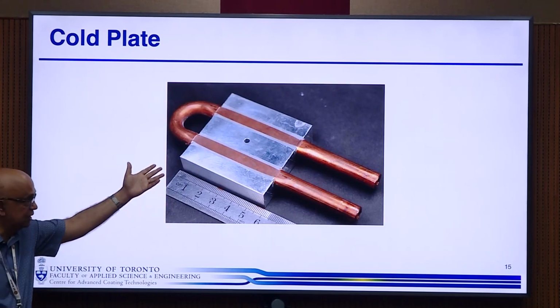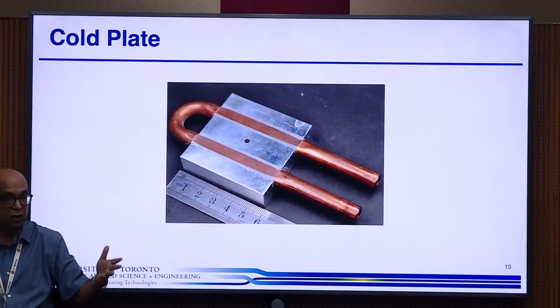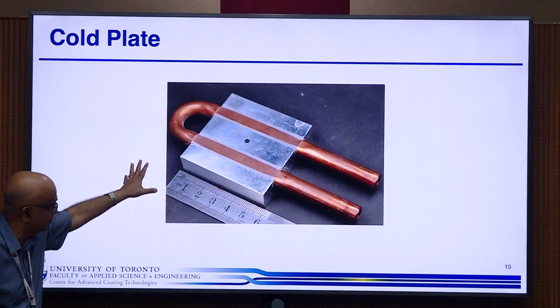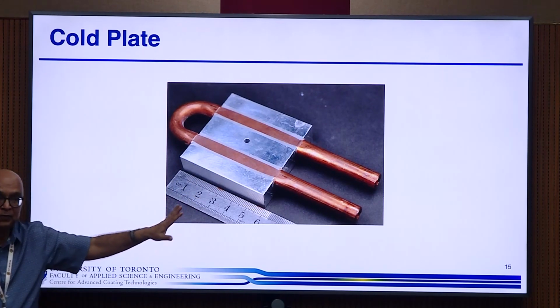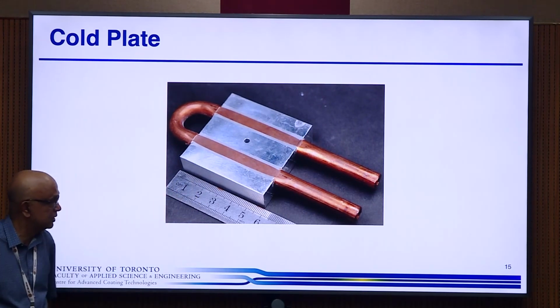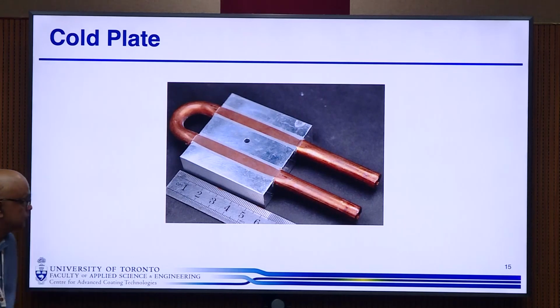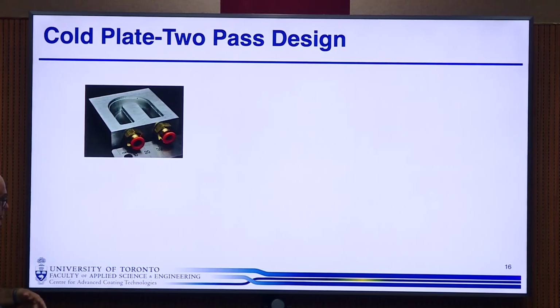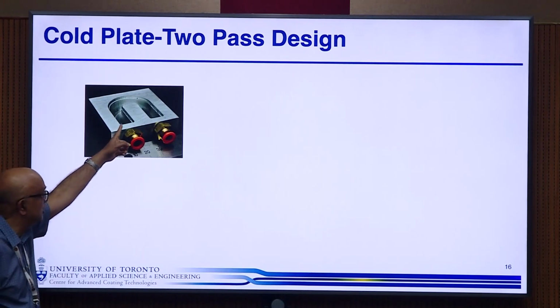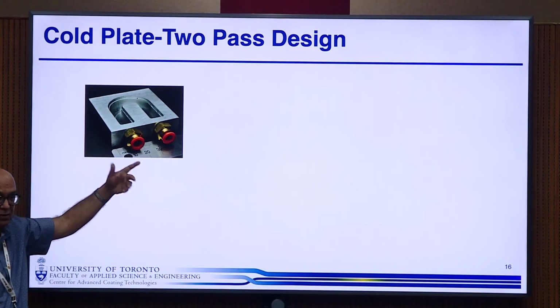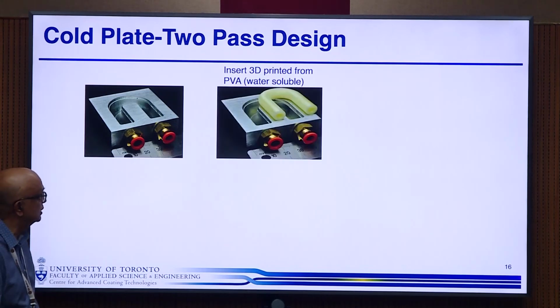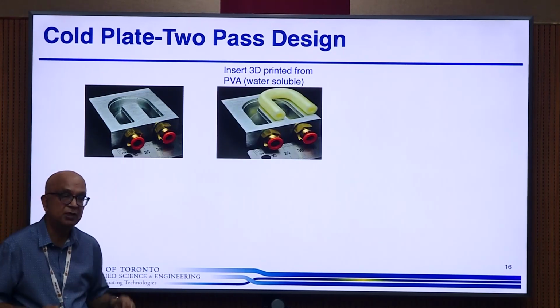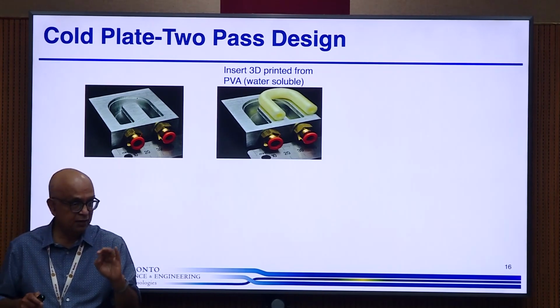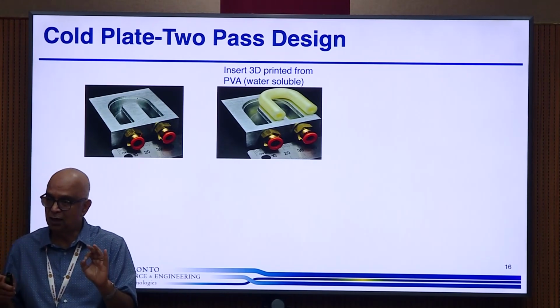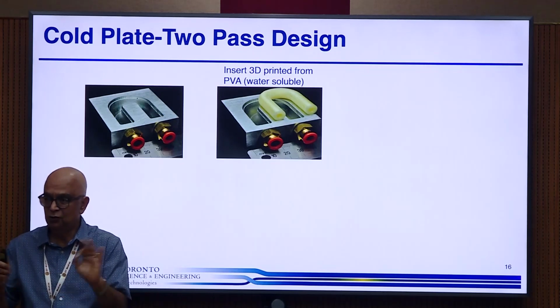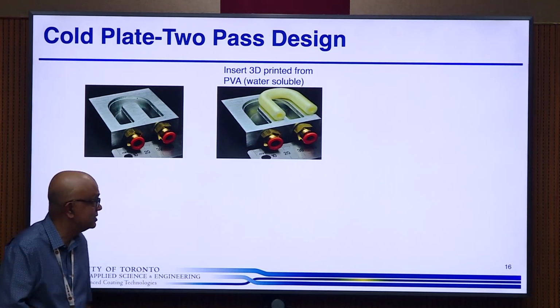So this is an off-the-shelf heat sink, which you can buy. I think it costs about $100 in Toronto. And it's very simple. So we started thinking, how can we improve on this? So the first idea was that we would take an aluminum plate the same size. You just machine a groove in that, and then you 3D print a tube. And this is made out of PVA, polyvinyl alcohol, which is a water-soluble polymer. And you can 3D print very nicely with this.